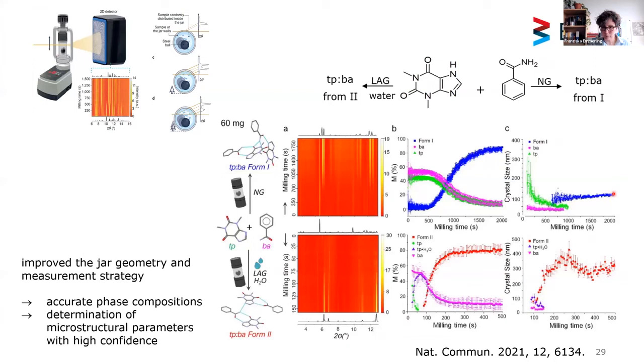If you perform the same reaction under liquid assisted grinding conditions using water in this case, we see a different behavior. Here you see in this violet color, in between we have the formation of the theophylline hydrate before we really produce the final form two here. So now with this high quality data, we are able to see these slight changes we haven't seen in the older experiment. And obviously, it is important that this hydrate is formed first. You see now here the intensity diminishes, and afterwards we have the formation of form two, which ends up at a higher crystallite size, around 300 nanometers.